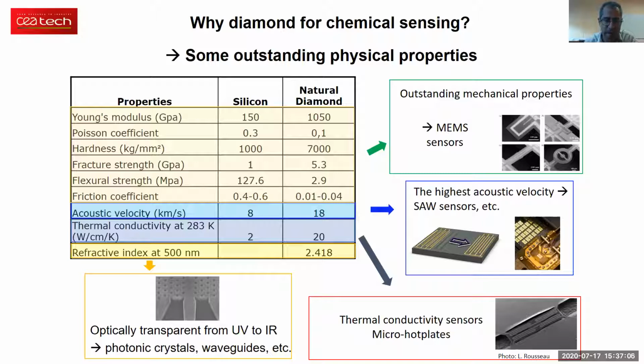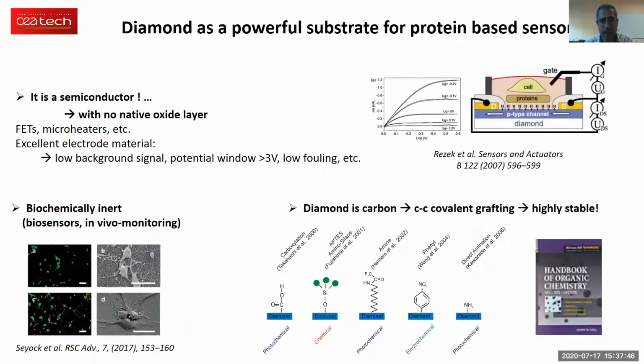I will be very brief here, but basically if we look at the physical properties of diamond, diamond is probably the best material in all the areas of physics. It's the most transparent material. This is a material that has the highest thermal conductivity, that propagates acoustic waves fastest. It has outstanding mechanical properties. If you look at the Young's modulus of diamond compared to silicon, for instance, it's about 7 times better. So that means we can use all these properties to enhance the sensitivity and the performance of our chemical sensors and especially our transducers. Diamond is also a powerful substrate for protein-based sensors.